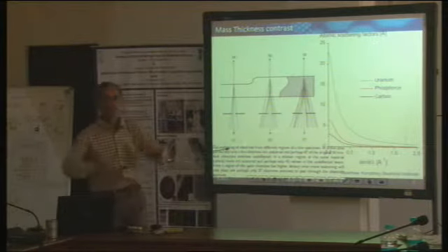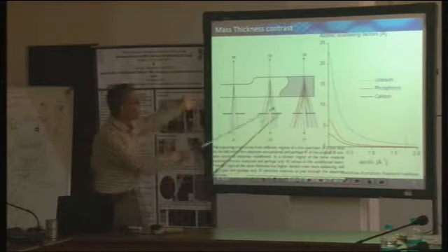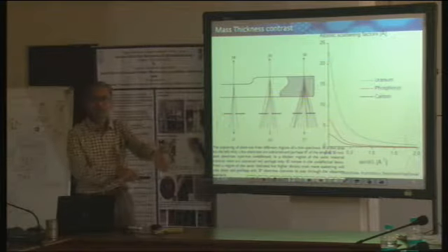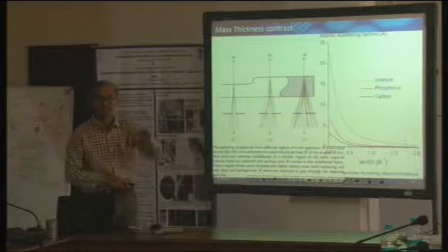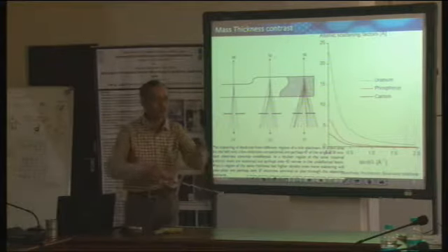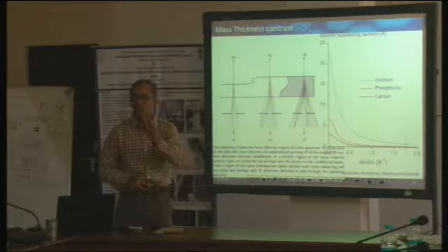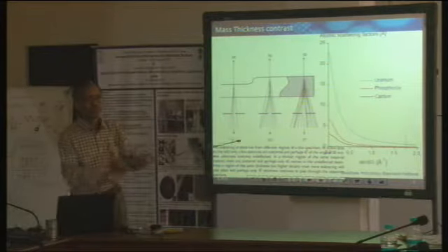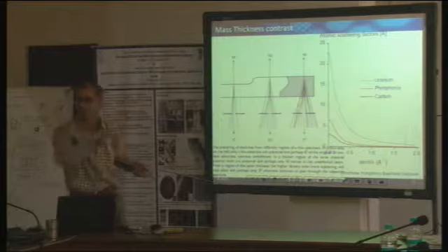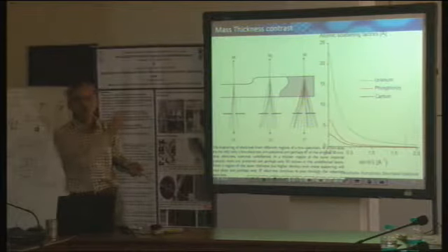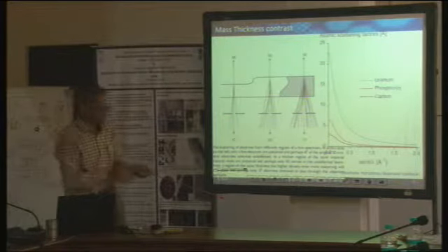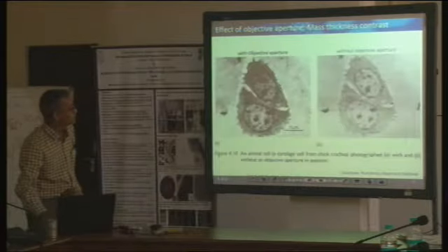So what will happen when the image is again formed? These scattered beams also come back to that image and form an image there. So scattering happens, but these scattered rays again come back to the image and contribute to the image. So effectively, although they got scattered, they came back to the image again. So there won't be any contrast because of the fact that there was scattering, and that is demonstrated in this